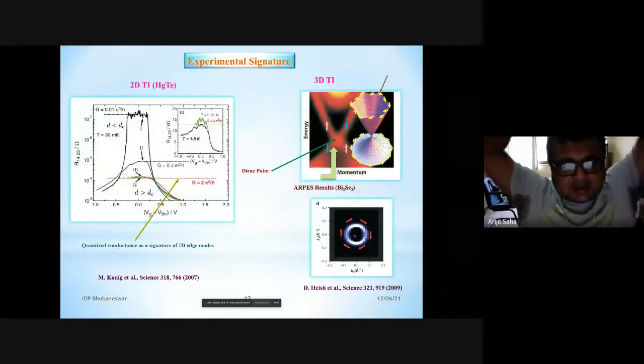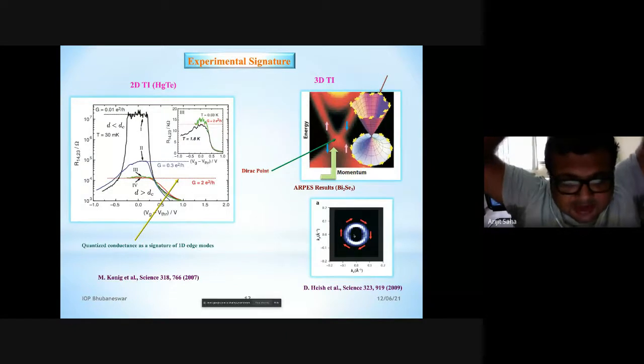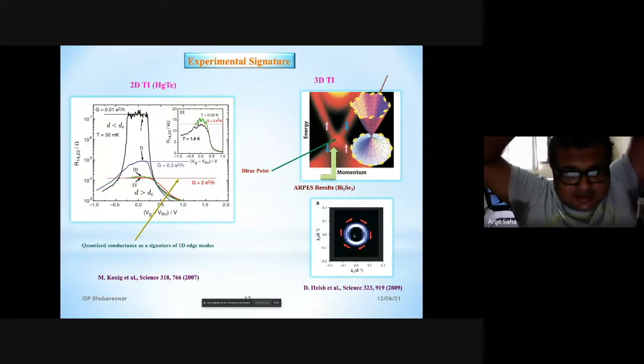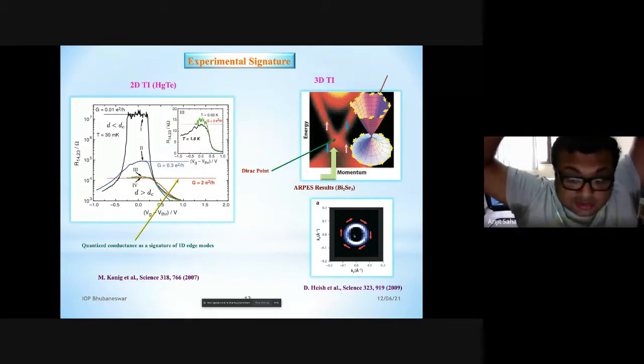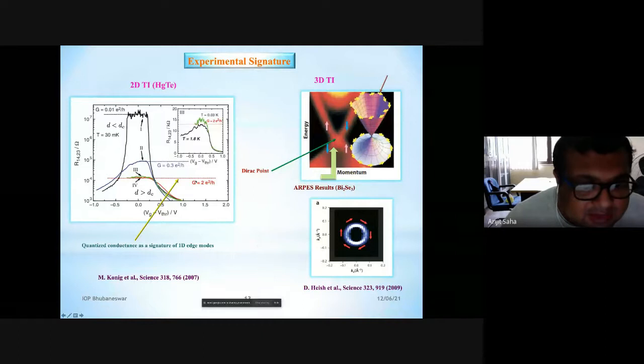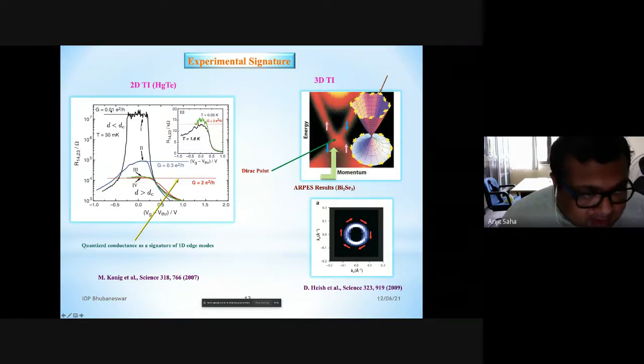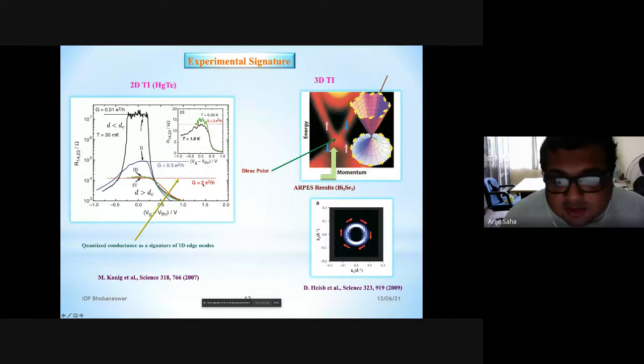So let me show you in experiment how they differentiate between these systems. For 2D, we already know that these are edge modes. So they performed the experiment in the exact geometry of mercury telluride that I showed, and you see that when you are in the trivial band insulating phase, your conductance is very small in units of e squared over h. But when you're in the topological phase, your conductance becomes 2 e squared over h. This 2 comes because of the two copies of the edge, up spin and down spin, spin-momentum locked edge modes. As there are two edge modes you get two, but in the quantum Hall you get only one.